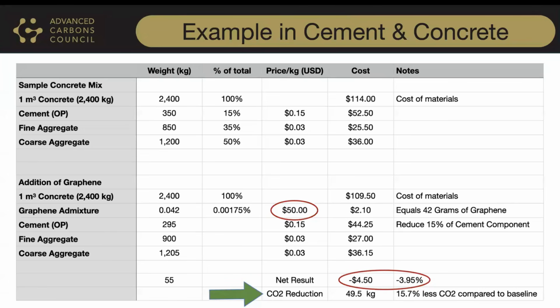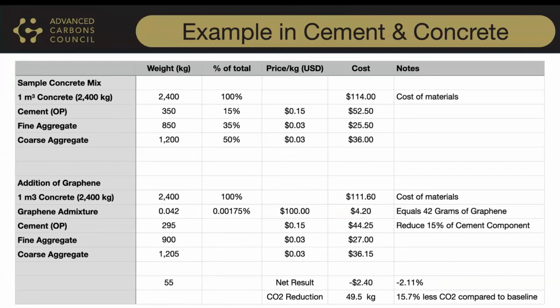So now if you're a ready mix producer and you're able to apply this, you can go to the market with a low CO2 cement that actually costs less for you to produce, where you could either sell it at parity with the normal grade material, or you could, of course, ask for a premium. Now, if we use a higher price material, $100 a kilo, we see that at the same load factor, you still come in under cost compared to the baseline, and you still have the same CO2 reduction.